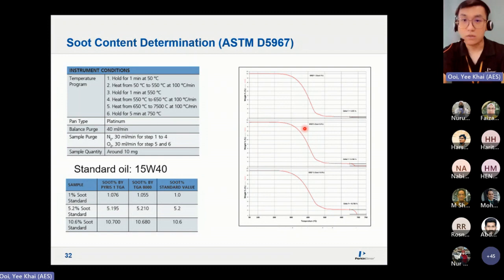So this is for soot content using TGA as well. Incomplete combustion of your lube oil actually forms carbon. Soot is actually carbon. So you need oxygen in order to run carbon analysis, as we mentioned just now. We monitor the percentage of soot based on the standard oil. You can use this to monitor very, very small percentages of carbon being formed. We use a standard oil with standard values, and then we verify with TGA, and you can see you get comparable results with the standards.